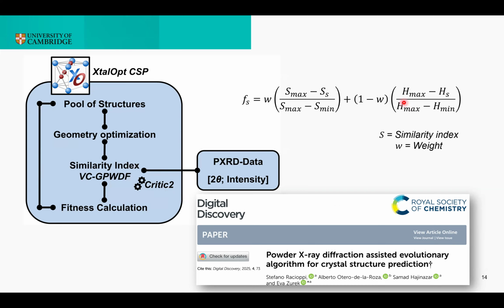Then a fitness parameter is calculated based on the multi-objective formulation that I showed before, done by Samad, by including the similarity index from this module. In this way, the crystal structure prediction will tend to generate the structures that better fit with experimental data, because now we're promoting those structures that have the right structural parameters, but also those atomic dispositions that fit with the powder diffraction, even if maybe they're not the most stable. Moreover, I want to add that the powder diffraction routine does not add any computational cost to the crystal structure search. In fact, this calculation takes only a few seconds on a laptop computer.